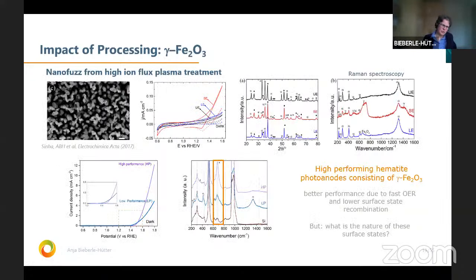Perhaps one short slide also, a bit of a side note, about the impact of processing. What we find now with two different kinds of processing, that usually in the literature is reported about alpha Fe2O3, but there exists also a gamma Fe2O3, which is usually not stable. But when we do high ion plasma treatment of the samples, and we can make these so-called nanofuzz structures, we also get an increased performance. We do not see differences between exposed and non-exposed samples in the XRD, but when we go to Raman, we can identify this gamma phase.